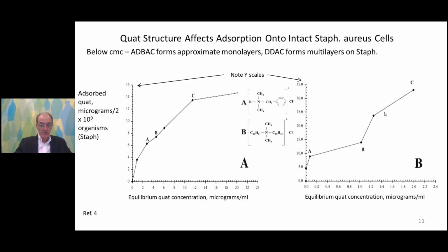And we've seen step-like isotherms like this when we talk about adsorption of surfactants onto inanimate materials. And that suggests that at lower concentrations, we may have the high energy sites for adsorption filled up first. And then as the adsorption isotherm jumps up, lateral interactions between the surfactants, the quat in this case, can lead to the formation of things like hemimicelles or even bilayers on the surface of the bacteria. So given that we've seen how heterogeneous the bacterial surface really is, it's not too surprising that we have these multi-step adsorption isotherms that are possible.